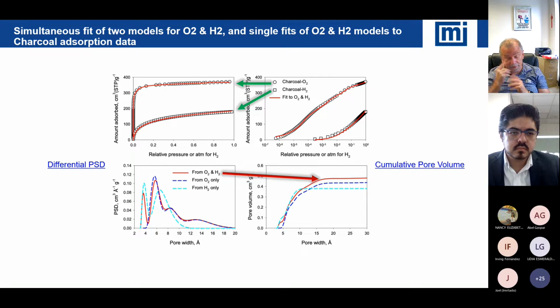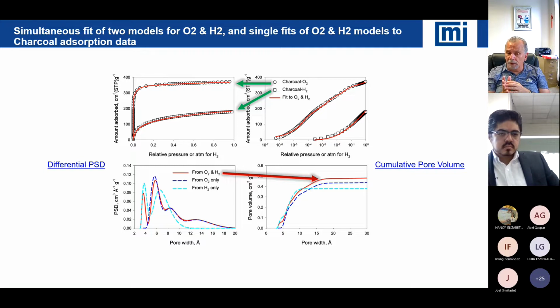The second one that goes along with it is, of course, when you make these materials, you could have very significant tortuous paths, and you could have occlusions. So, looking at the pore size distribution of a formed material from the powder, they may not overlap as well because you could have quite a few occluded pores. You're definitely going to create some new pores. Naturally, you're going to introduce a lot of macro porosity that you may not see in the powder. Adsorption in those macro pores is quite fast, so there won't be any serious concerns about that. But there's definitely going to be a new pore structure because of the way the particles are put together. And again, it's strictly a bit more patience and making sure the sample is fully equilibrated.